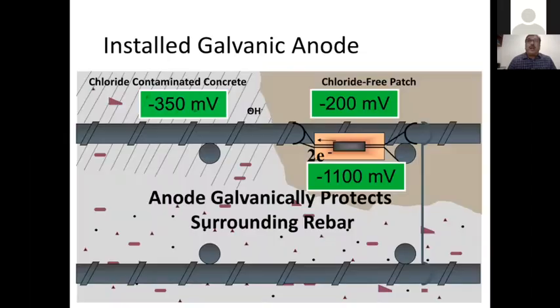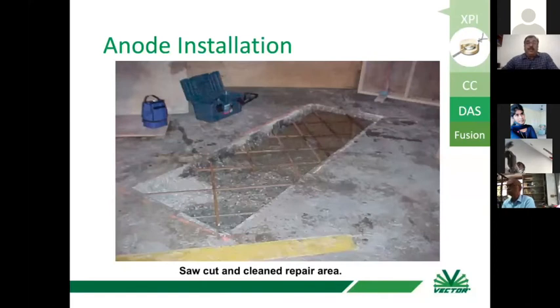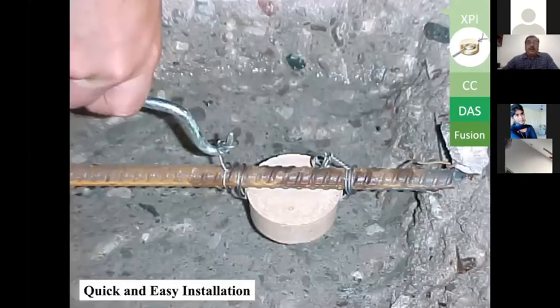The zinc will corrode because of very high negative potential, and it will not allow the reinforcement to corrode, and you can have a durable and good patch repair. This is how we do a normal patch repair: proper cleaning, saw cut and soaking, and apply the mortar. The additional thing is you just have to tie an anode like this.